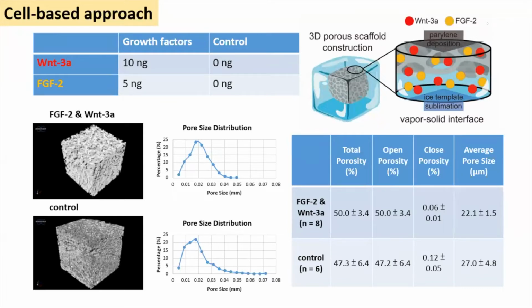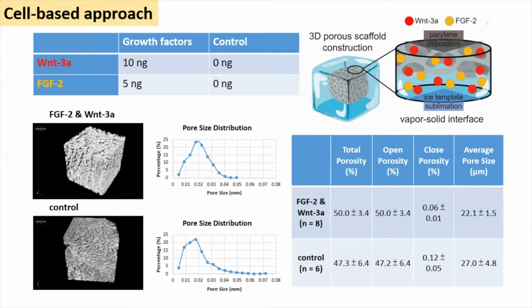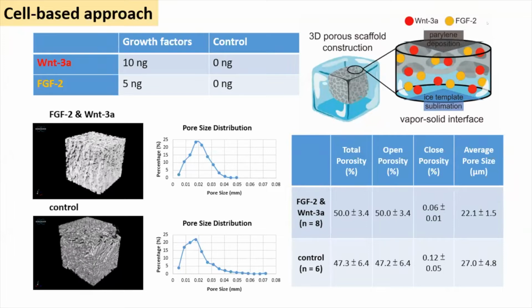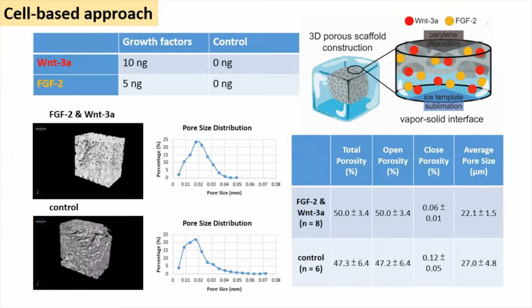During the sublimation process, the pores inside the parylene material can be formed, and the growth factor can be left in the porous space. The porous structure would then provide the space for culturing the stem cells. So we denote the parylene-based material as PPX here. And then we measured the PPX scaffold by micro-CT and found the PPX had ideal pore space and pore size and a good porosity ratio.